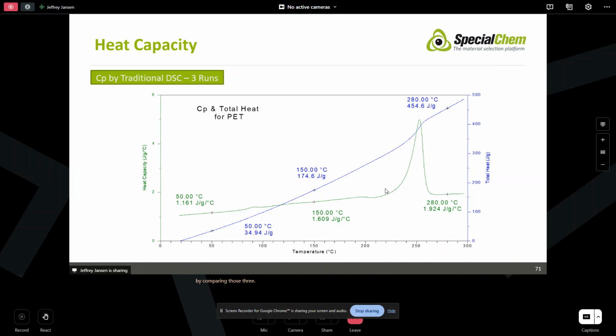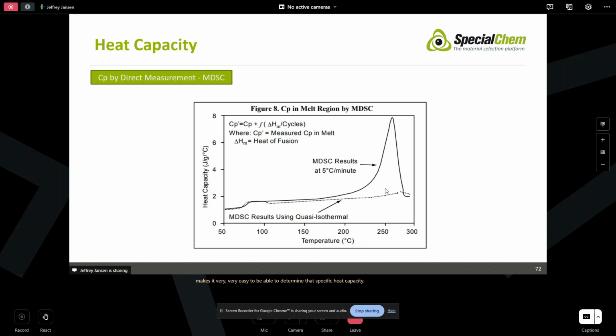Newer pieces of equipment allow you to do that basically all at once, okay? And so we can get that information all at once by looking at the heat capacity of the material over a temperature range. So you can understand what it is at different temperatures through that heating cycle of the material. Again, it makes it very, very easy to determine that specific heat or heat capacity of the material. Typically, that's done in the new instruments using what's called modulated DSC or MDSC.